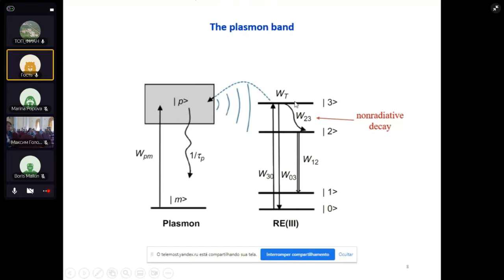Another point is that non-radiative transitions are also very important, non-radiative transitions in the rare earth ion. And so we have a competition between these phenomena, these channels, these processes, in setting up an appropriate system of rate equations. If we are interested in quantum emission, quantum yield, and so on, we should pay attention to these facts.